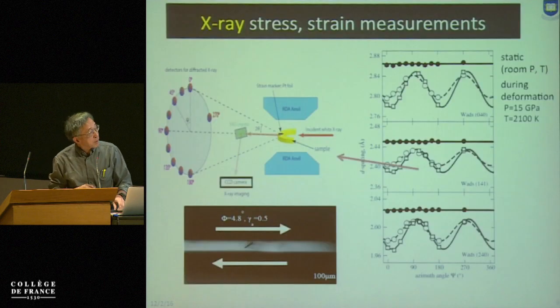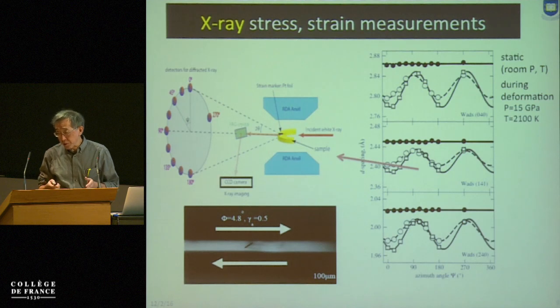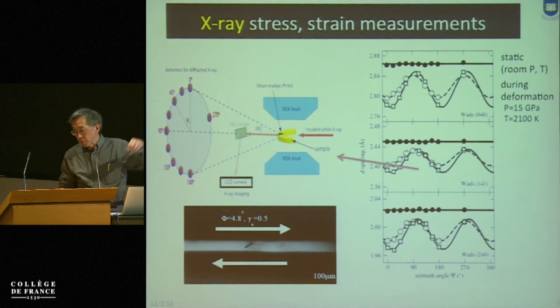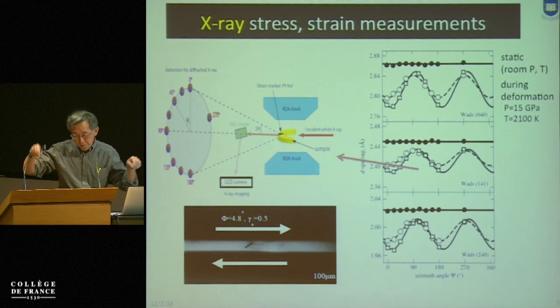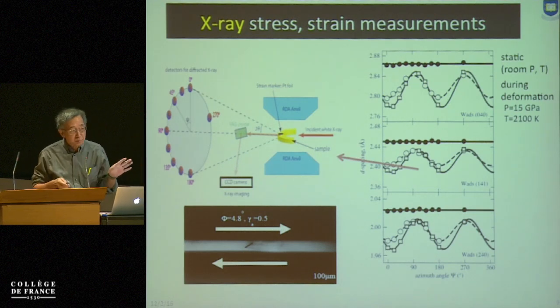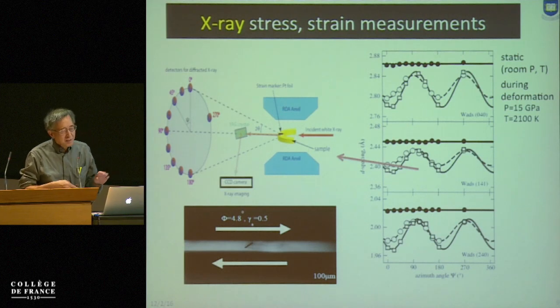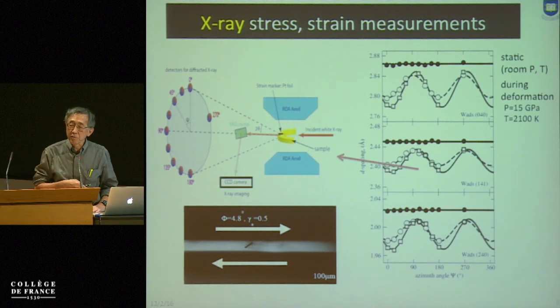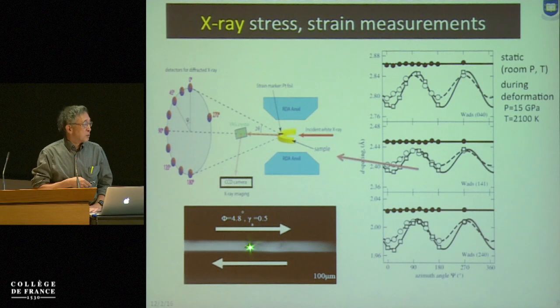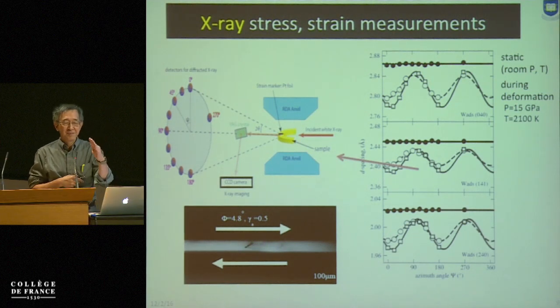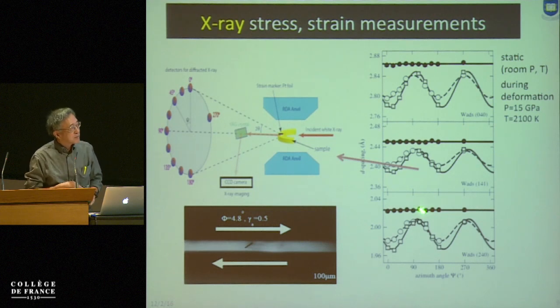So this is a way to measure both stress and strain in situ, rather than measuring stress by a load cell or strain by displacement of something. No, this is the in situ measurement. This is remarkable because one of the fascinating things about doing those experiments is that during the experiment you can see your sample. Wow, my sample is rotating. This is fantastic. And then you can determine the stress, and also pressure and temperature.